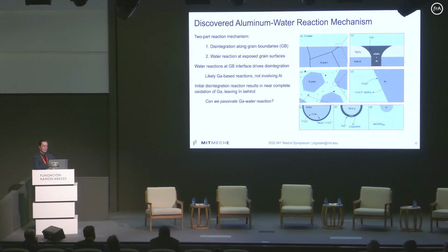First, the aluminum is disintegrating along those grain boundaries, and that's the result of some initial reaction that's happening in the liquid metal intergranular phase. And then now you have all this surface area that's exposed, and there's no oxide layer on those internal surfaces of the bulk aluminum, so the aluminum water reaction can proceed uninhibited from there.